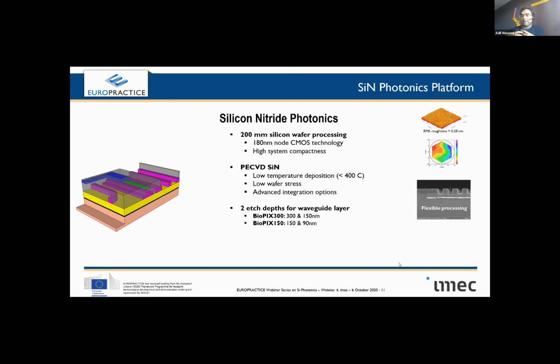And the MPW processes which Imec offered converged on 300 nanometer thickness and 150 nanometer thickness to cover the wavelength range of 700 nanometer to 1000 nanometer in the case of 300 nanometer thick silicon nitride, and roughly 350 nanometer to 700 nanometer wavelength range for the thickness of 150 nanometer silicon nitride.